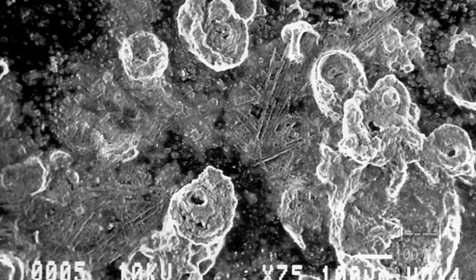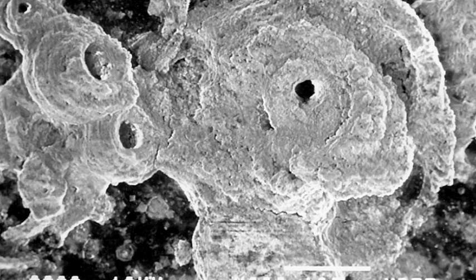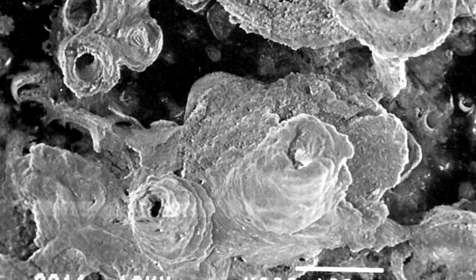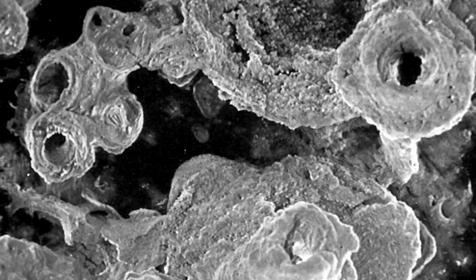In the electron microscope, the white corrosion product on the surface of the corroded aluminum now develops certain features. We can see that now there are mounds and tubes and chimneys poking off at the surface. And these are the chimneys we described earlier where the hydrogen bubbles pump the aluminum out and they react with the water to form the aluminum hydroxide.